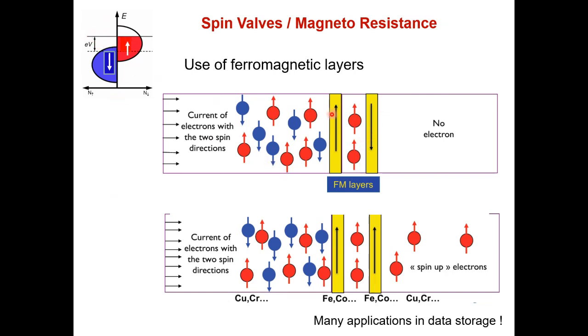So let's say that we put two ferromagnets with different magnetization. So here only the red spin can cross, and here to cross you need to be spin down, but they're only spin up. And so there is no way to cross the second ferromagnet. And so you see that there is no current flowing across the device. And this is just controlled by two electrodes, not three like a transistor.